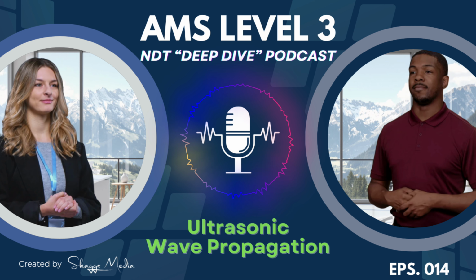But you mentioned things like advanced composites or certain alloys. Those can be anisotropic. Right. Anisotropic means properties depend on direction. How does that mess things up? Well, it gets significantly more complex. Because the elastic properties change depending on direction, think about wood grain, or fiber direction in a composite, these materials can actually support three distinct body wave modes. There's one quasi-longitudinal mode and then two different quasi-transverse modes, each with its own velocity.